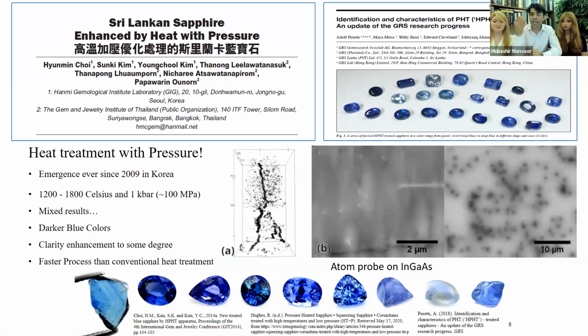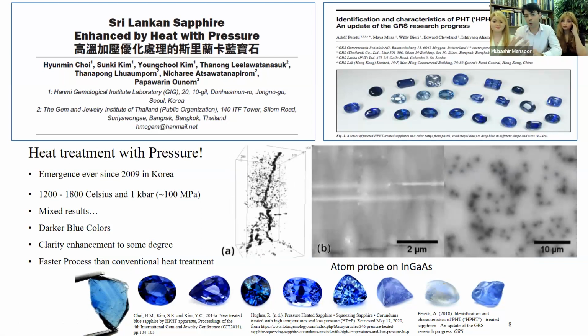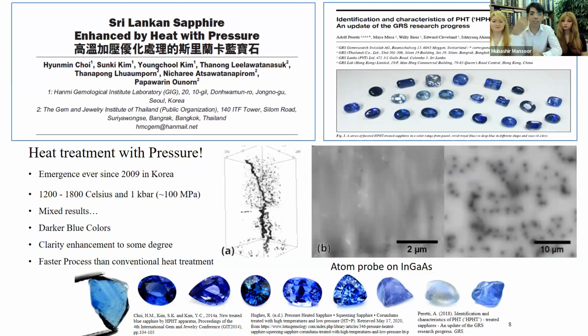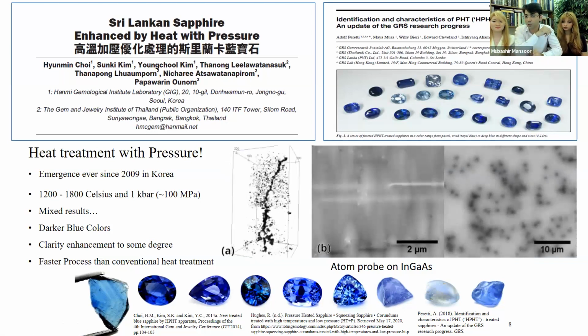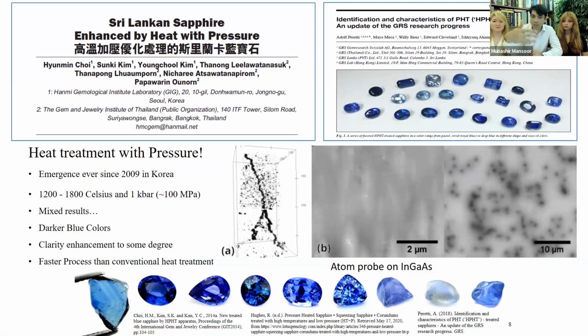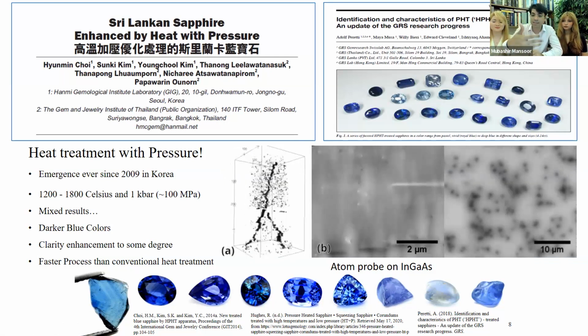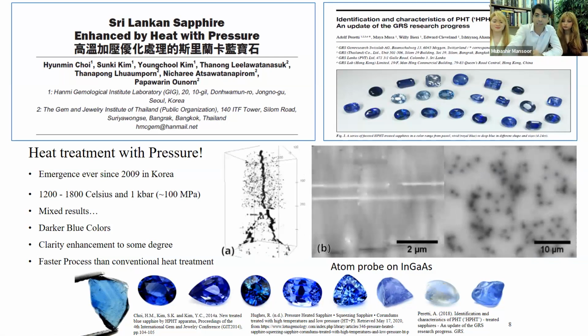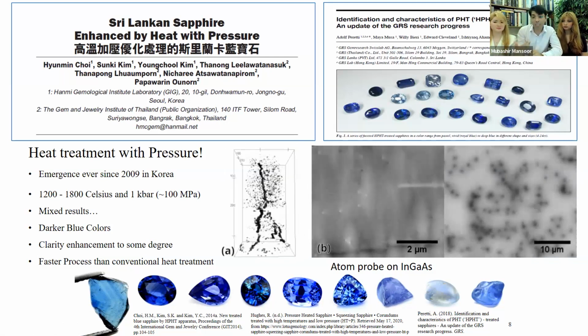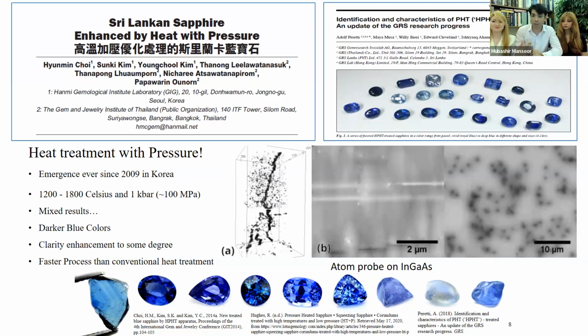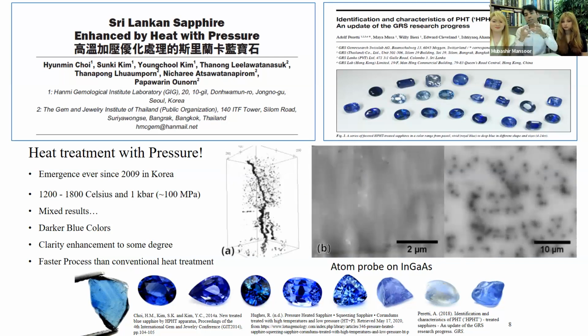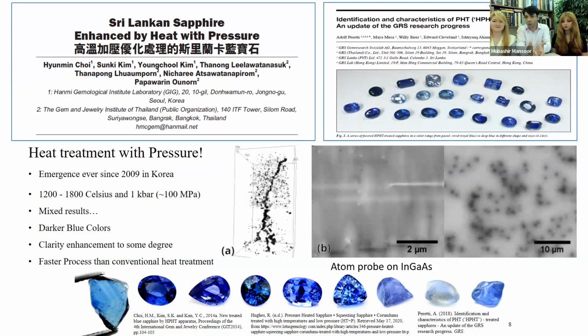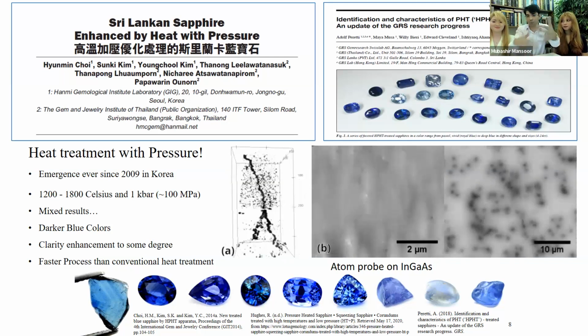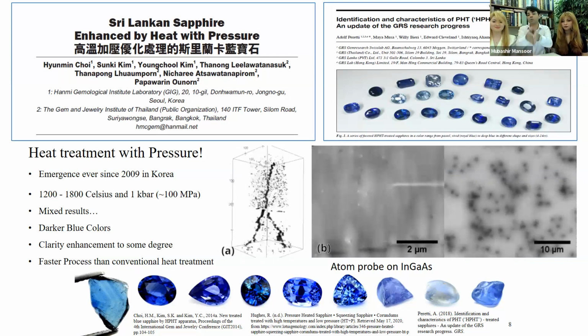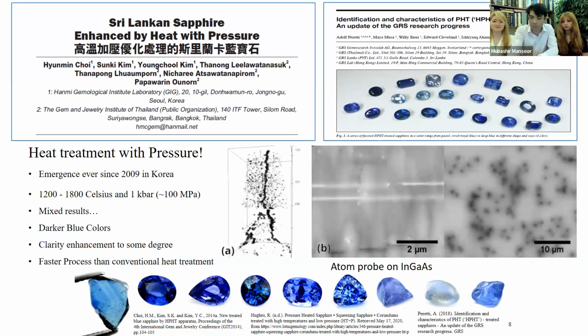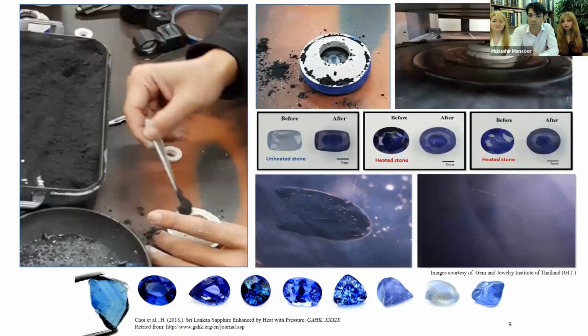And that means if some process was taking long, now because of these highways, it only takes a matter of minutes to be completed. So the incorporation of pressure actually creates these additional defects that tend to enhance the speed of the treatment process by a lot. And that also means you can dissolve even more of your rutile easily because the process has become very fast. And that means you will be able to get darker colors. So in principle, it's actually very easy to explain why this process is more effective.